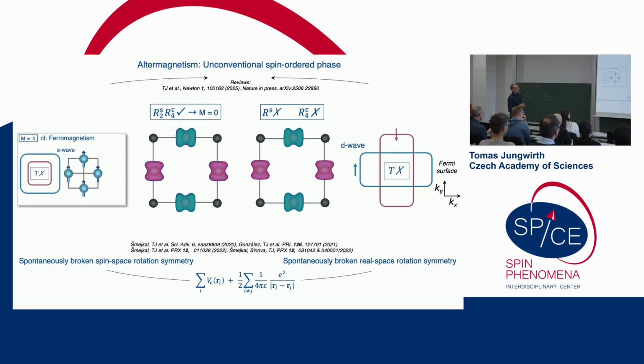Now, apart from the spin space and real space symmetries being broken, there is one very important symmetry which is also broken in an altermagnet. And here we don't have to get into the discussion whether it's in the momentum space or in the direct space, because it's actually in both. We have the broken time reversal symmetry. Now, that is reminiscent of ferromagnets, where also we break the time reversal symmetry in both the direct space and the momentum space.